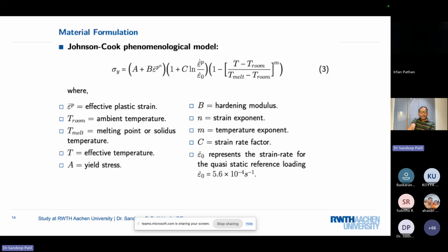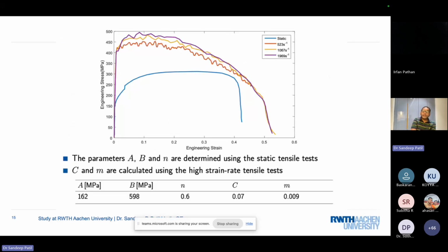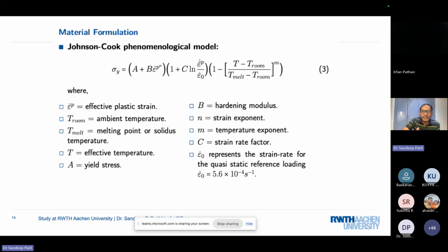This is very interesting. Just to not go into detail, I can explain how we can get the parameters of the Johnson Cook, and in our paper you can also find this material model explained in a more detailed way. So parameters A, B, and N. If you look here, A, B, and N are yield stress, hardening modulus, and then C is a strain rate factor. N is the strain exponent.